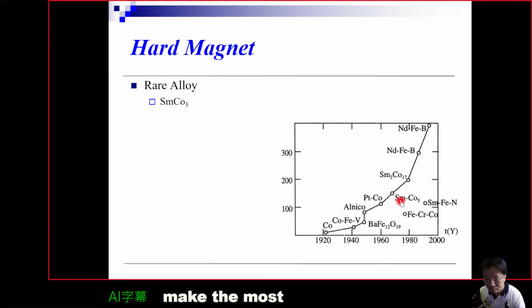So after the 1980s, people knew we could make rare earth alloys. Okay, it's not rare alloy, it's rare earth alloy. We can make a hard magnet with a rare earth element. The first rare earth magnet appeared with samarium mixed with cobalt. The idea is that we already know cobalt is a very good magnet. If we mix in some samarium, maybe we can induce magnetic order in the samarium, which contains 4F electrons. So we may create a very huge internal magnetic field, and that would become a very good hard magnet.